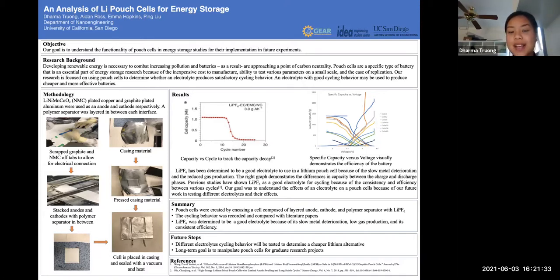So we put the cell inside the casing, and we sealed all sides with the exception of a small hole. And we will later insert electrolyte into the small hole. One side is sealed further than all the other sides to form a gas valve. The electrolyte will react with the cell and create gas, which is why extra space is needed to disperse the force caused by the gas formation. And later on, we will go back in and cut off that gas valve.